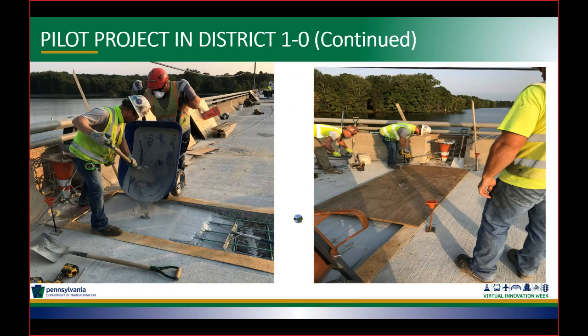Here's a photograph of the actual placement. The interesting thing about the UHPC is it's a fairly flowable material, but it has kind of a sticky nature to it as well. As you can see there, they actually have to use a shovel to scrape the material out of the wheelbarrow. But if you look in the joint itself, the material is actually flowing out. So the slump on this was fairly high. It was about an 8 or a 9 inch slump. And so it is fairly flowable, but yet at the same time, it needs some help trying to get out of the wheelbarrow.